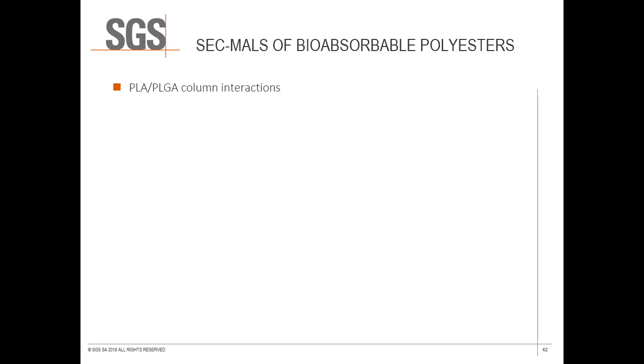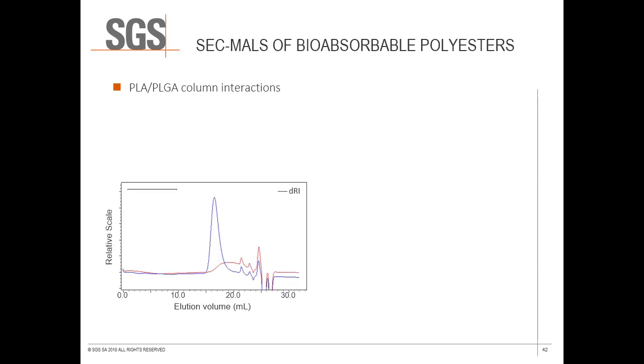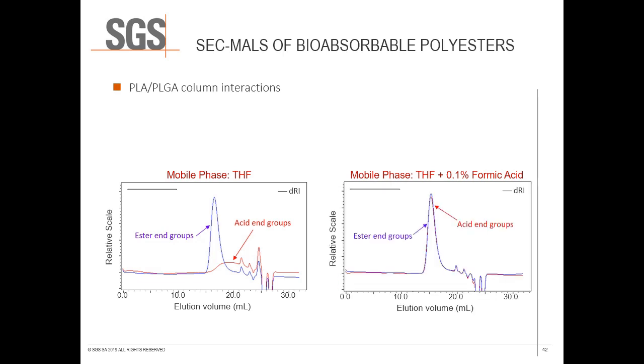An earlier PLA analysis produced some disappointing results for samples with acid end groups of approximately the same molar mass as PLA samples with ester end groups, as shown in Figure 1. We performed some investigative analyses with and without formic acid as the mobile phase modifier, with drastic results, shown in Figure 2. If analyzing organic soluble acidic polymers, acidic mobile phase modification may be necessary to prevent the ionization of the polymer and the subsequent column interactions.